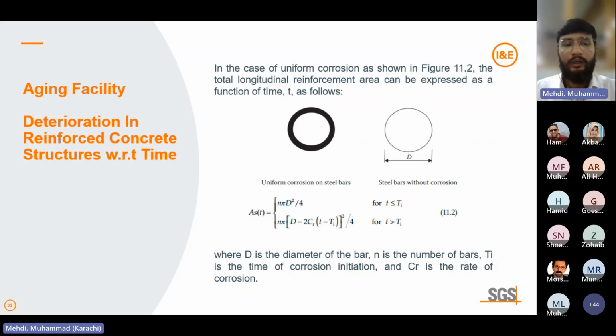Similarly, if you talk about the reinforcement, without corrosion the rebars have their minimum nominal diameter. But when corrosion starts and the degradation process begins, the material degrades due to moisture or oxidation, starts to disintegrate, and this results in capacity loss in the reinforced concrete sections. In the fundamentals of the design of any reinforced concrete member, the member's capacity depends on the cross-sectional dimensions of the concrete and steel area, and the material strengths: concrete strength and steel yielding strength.